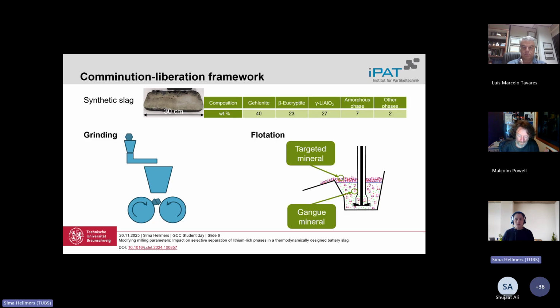So let's move to the first one. The first step was the comminution liberation framework. For this one, I used different slags, and most of them were synthetic. That is, different oxides were used to produce a slag similar to lithium-ion battery recycling slag. The main phases were gamma-lithium aluminate oxide and beta-eucryptite as the phases that contain lithium, and then gehlenite as the gangue material.